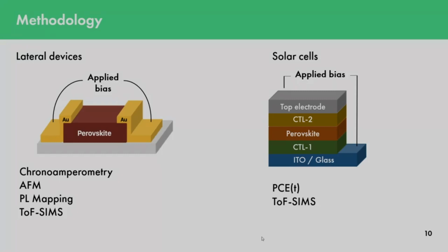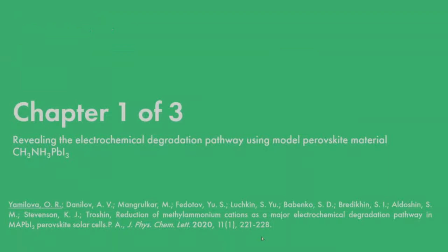And of course, we made the other kind of devices, solar cells, with a traditional configuration. We used mostly ITO on glass, which was commercially purchased, and most of the materials were not synthesized, especially the charge transport materials. They were purchased. So the perovskite is placed between two charge transport materials, and we have two electrodes, a top metal electrode and a bottom transparent electrode, ITO. These devices were investigated by observing changes in the efficiency of solar cells over time. And TOF-SIMS was also used as the most informative method for such devices.